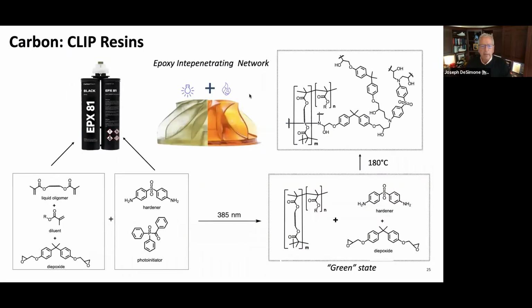And just to give you one example, you can take a free radically curable system like these methacrylate based systems, and you can have about 10 to 15 or 20 volume percent of this component, and you can have it with the traditional step growth polymerization here, a diepoxide and a diamine. Here we're using an aromatic amine. It's a little bit longer pot life. They don't have to worry about Michael addition here with the methacrylates. But you can basically combine all this chemistry.